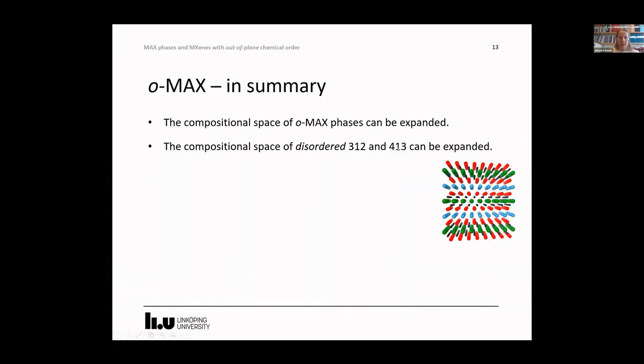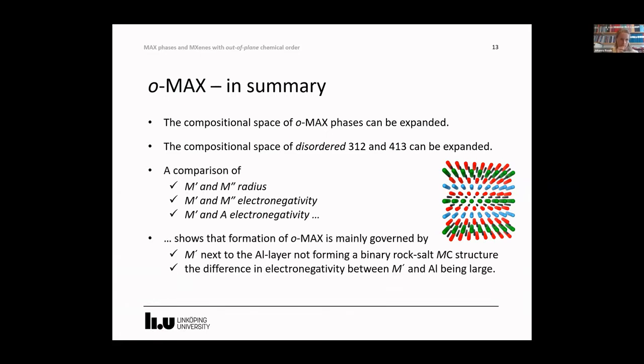So to summarize the work on the OMAX, I have suggested through the results that the compositional space of OMAX can be expanded, and also that the compositional space of disordered 312 and 413 can be very much expanded. What I haven't shown here is that we've made a more detailed analysis where we have compared the M element radius, the M element electronegativity, and also the M prime and A electronegativity. And the results show that for most known and predicted OMAX phases, the formation of OMAX is mainly governed by the M prime next to the Al-layer not forming a binary rock salt metal carbide structure, and that the difference in electronegativity between M prime and aluminium being large.